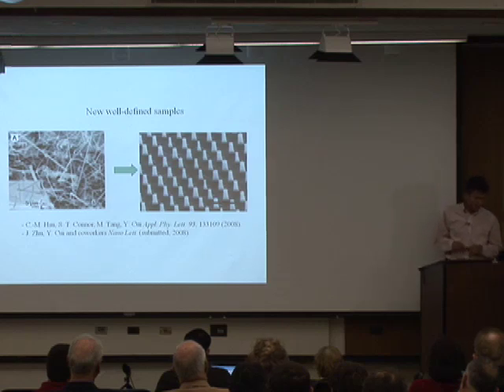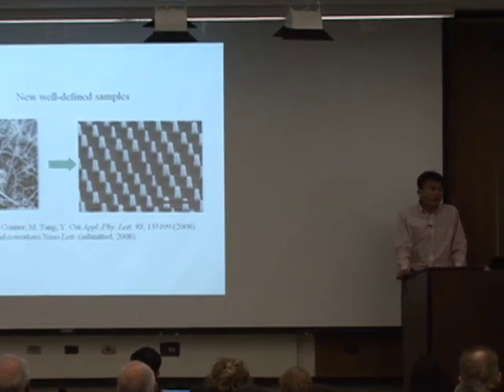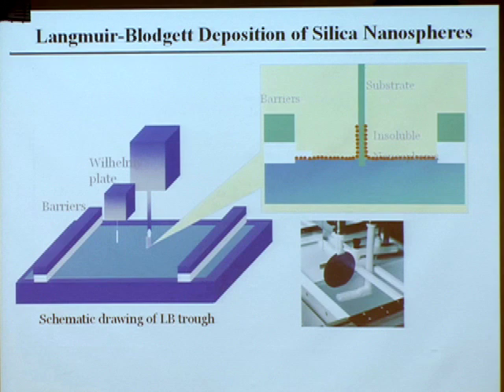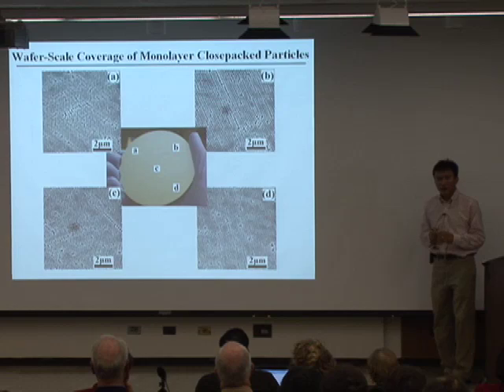to develop the technique to make this nano pillar. But the story I'm going to tell you is, as soon as we get this pillar, some other exciting things happen. This is always how the science develops. You think about some other things. It turned out this structure is very good for solar cells. So the way we made this structure, we produce these silicon dioxide nanoparticles. We functionalize the surface and float them onto water surface, form a monolayer. So you compress these particles, they form a close-packed monolayer. Now you dip a substrate, this can be a silicon substrate, into this solution. And you just pull it out, you get a monolayer of particles on the surface of this substrate. This is how they look. This is a 4-inch wafer. You look everywhere on the substrate surface, you always see a nice monolayer of particles.